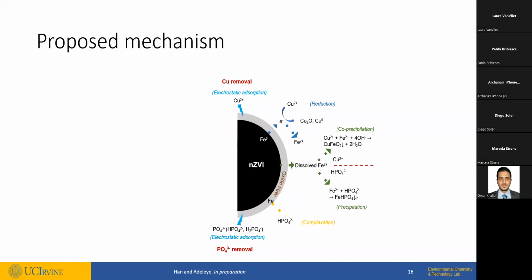And what makes this important? If you go back to the copper side, the byproduct of many of the reactions that lead to copper removal leads to the production of Fe2+. So here as an example, Fe2+ is a product of copper removal, but at the same time, it is a reactant in phosphate removal. So try to remember your basic chemistry. You have an equation where you have reactants and products. If you are taking out one of the products, based on Le Chatelier's principle, you are essentially driving the reaction to the right. So every time phosphate takes some Fe2+ and precipitates FeHPO4, it is driving the reaction that leads to removal of copper.